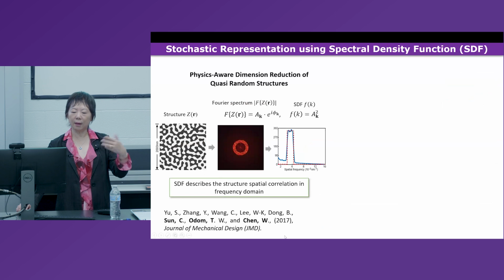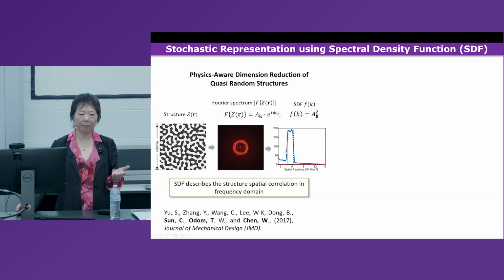For this nanodielectric material design, before we do optimization, we also have to handle the high-dimensional morphology. We're using a transformation technique called the spectral density function to transform this very complex structure to the Fourier spectral domain. In this case, it becomes a step function, and now we only need 2 variables, the lower bound and the upper bound. So it's a huge dimension reduction.